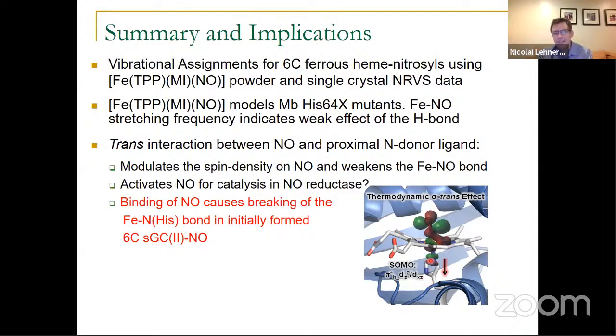And we can understand the nature of the trans effect, so that binding of NO here to the heme induces this antibonding interaction between the iron and the imidazole. And you can see with the arrow here that induces breaking of this bond, which moves this alpha helix here further away from the heme. And that essentially, this motion then induces the conformational change in soluble guanylate cyclase that leads to the activation of the catalytic domain.